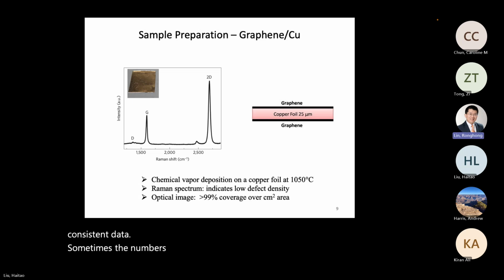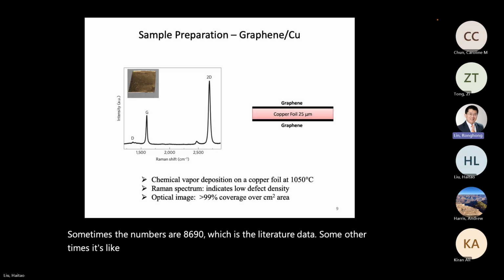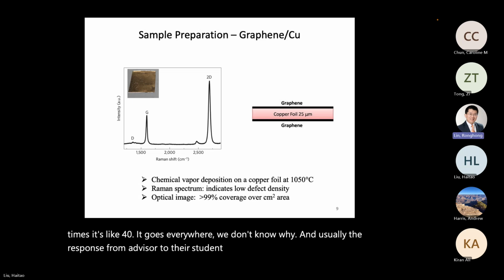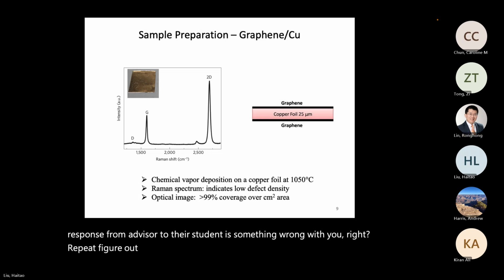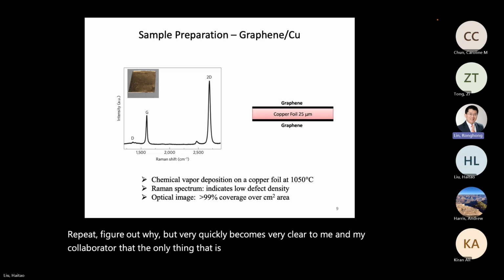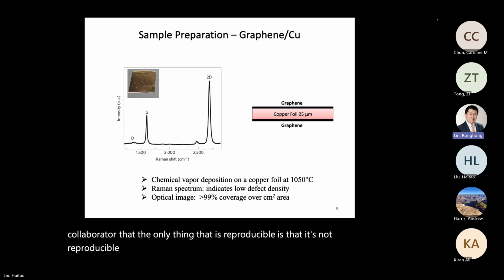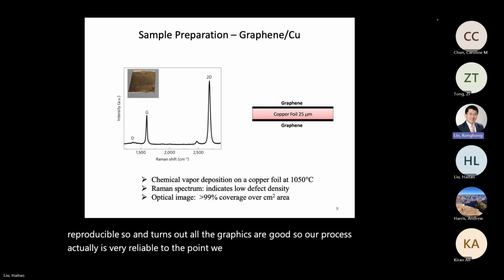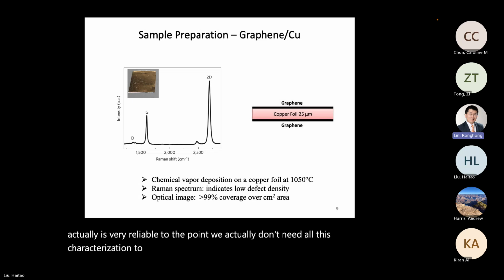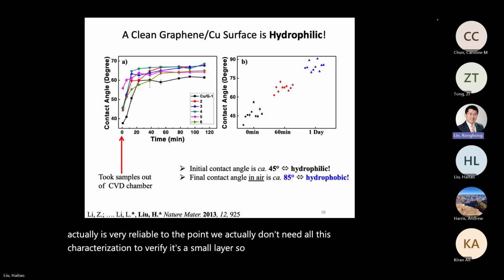Sometimes the numbers are 86, 90, which is the literature data. Some other times it's like 40. It goes everywhere. We don't know why. And usually the response from advisor to their student is something wrong with you, right? Repeat, figure out why. But very quickly it becomes very clear to me and my collaborator that the only thing that is reproducible is that it's not reproducible. And it turns out all the graphene are good. So our process actually is very reliable to the point we actually don't need all this characterization to verify its monolayer. So we got curious and eventually figured out why.